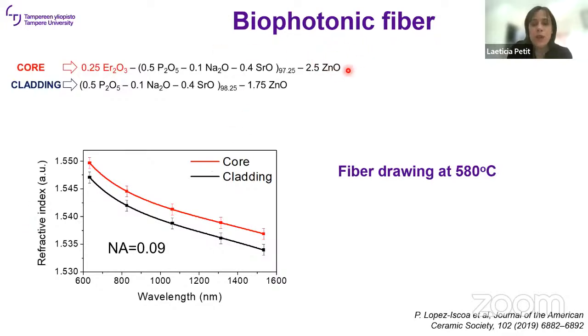So we went back to the composition with the zinc. So we tried to do this core-clad fiber. So the core has this composition. So the zinc, because it's promising, and this 0.25% more of erbium. And then to reduce the refractive index, we did the cladding with a lower amount of zinc and no erbium. So you have here the refractive index of the core, or the glasses used for the core and the cladding, as a function of the wavelength. And we have an NA of the fiber of 0.09.